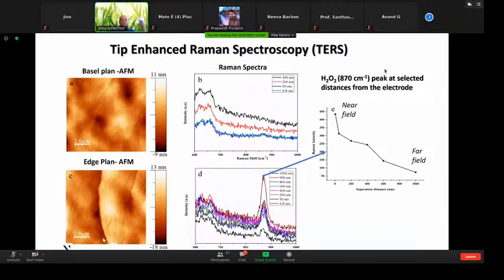Whereas if you look at the defects here, we know that now the defects create more oxygen sites. We see that as we go from 1,000 nanometers to 4 nanometers, we can enhance significantly the hydrogen peroxide detection. So this is a near field, and as we go further, this is the intensity of the peak. The peak grows significantly.